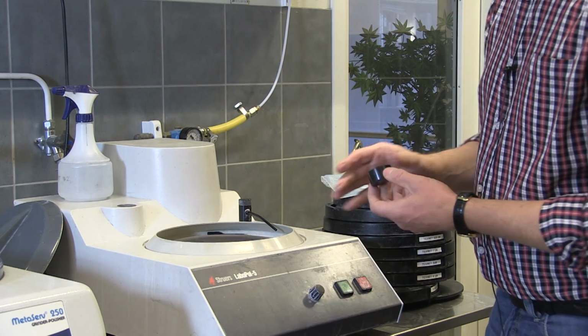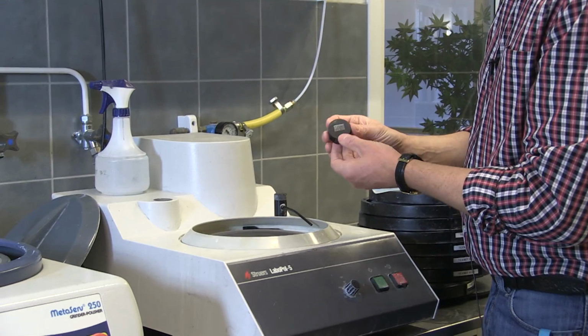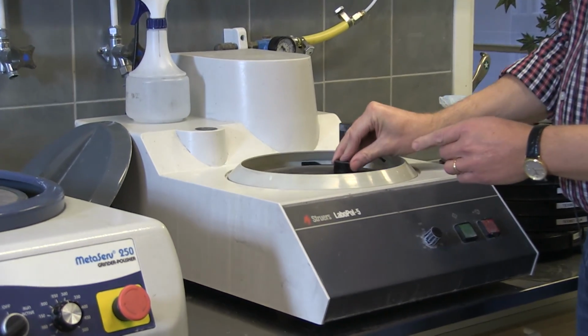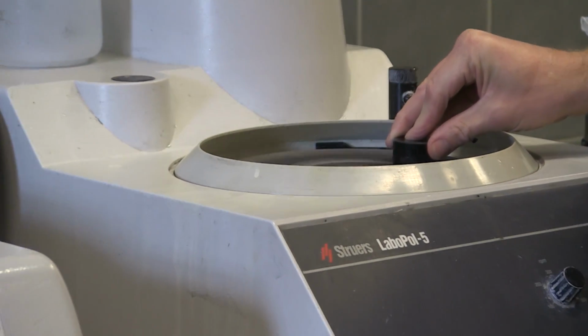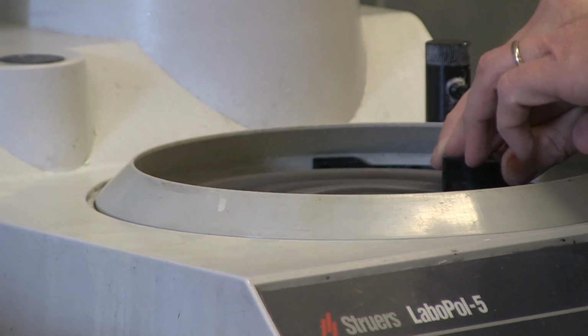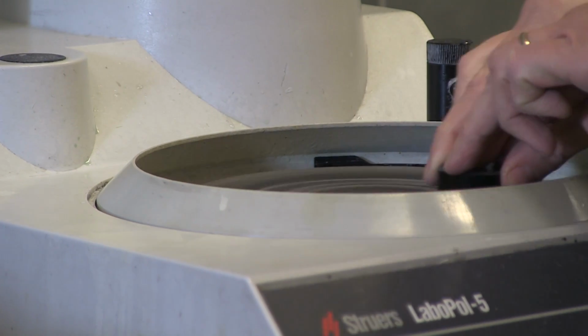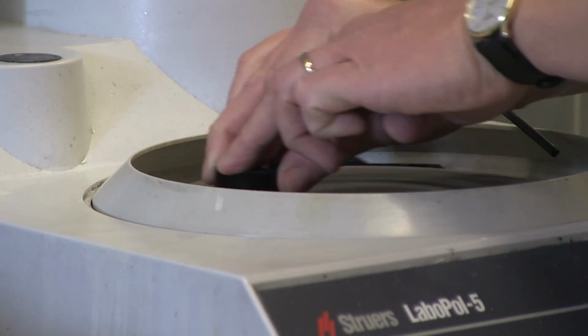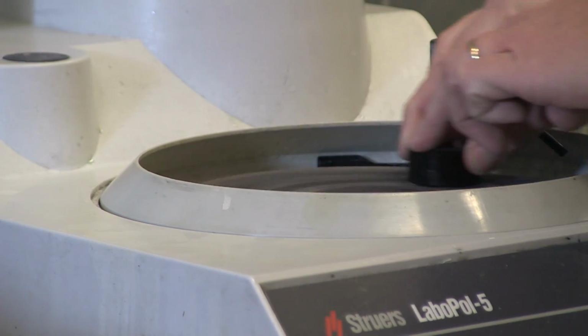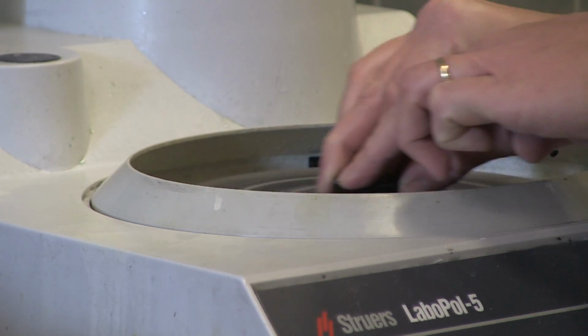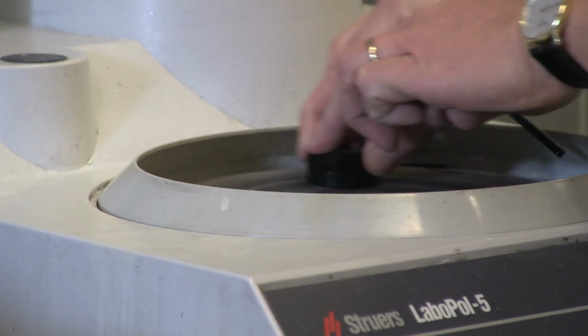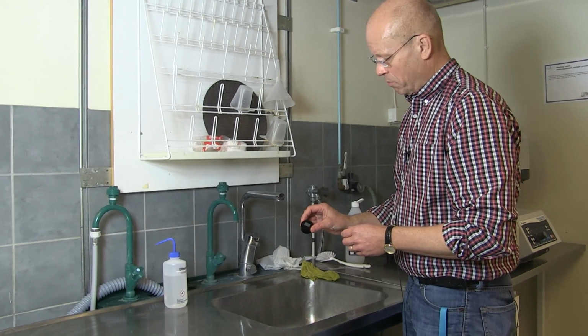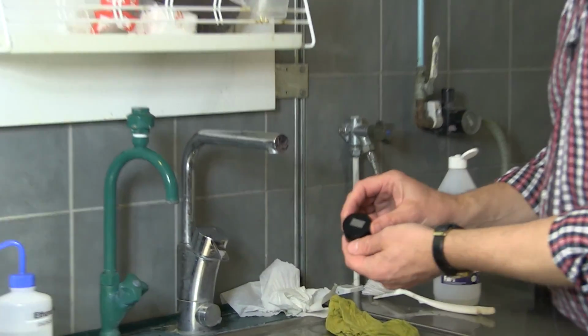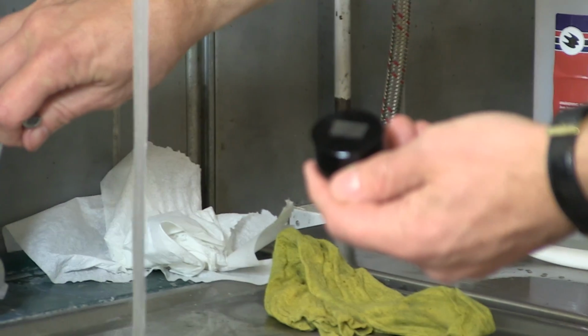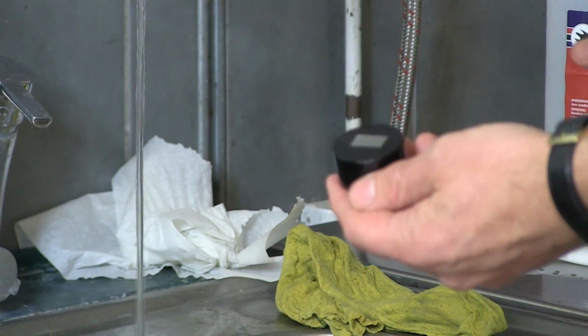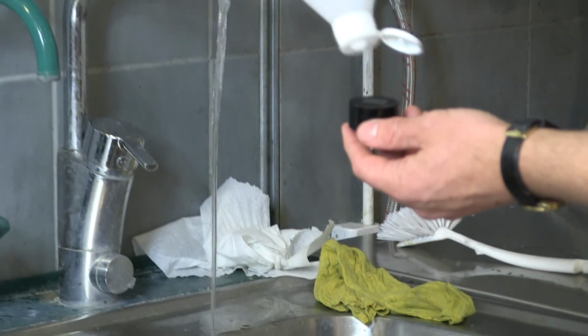So with the wet surface, 9 micron cloth, I start polishing, and I change tactics compared to when I was grinding. So instead of holding it still, I move it around like this. I move it in the opposite direction compared to how the wheel rotates. So between the polishing steps, it might be good to clean the sample a little bit better with a little bit of soap.